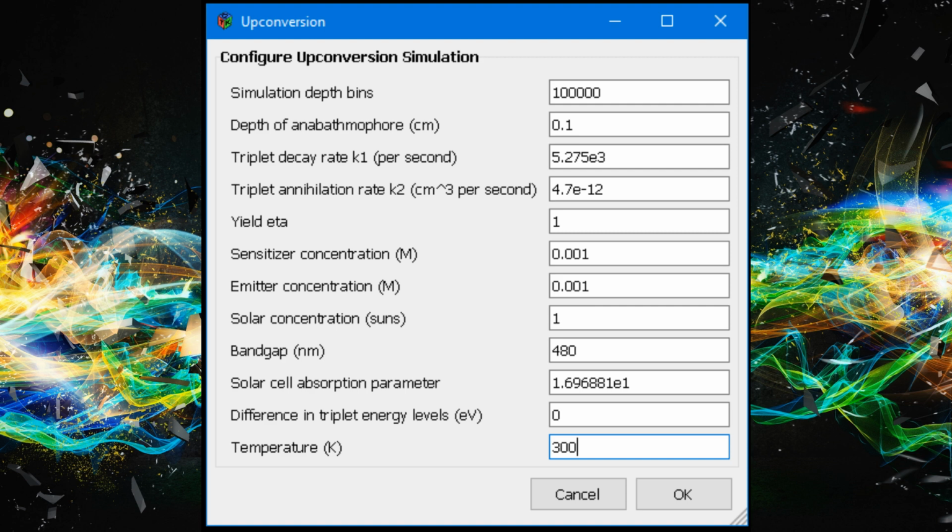When you're adjusting this value, you should keep in mind that it's very easy to introduce a lot of systematic error in this value by relying on experimental results. It's quite difficult to measure this rate constant, and very often those measurements have not been reproducible from lab to lab. So your choice of K2 is likely to be the largest source of systematic error in your calculation.